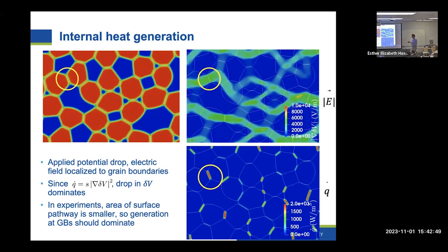So experimentally, we expect that the area of any surfaces is going to be pretty small compared to all the internal areas, especially if you're looking at a half meter compact, right? So really it's the generation of heat within these grain boundaries that's going to dominate.